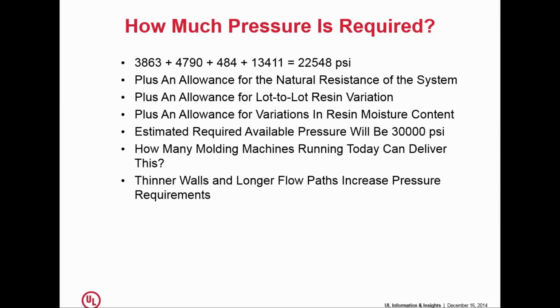And to move the screw, even if there's no plastic in the barrel, if you move a screw that's empty through an empty barrel, you will still get a pressure reading. And that pressure reading is just the natural resistance of the system, the natural inertia of the system. And for different machines, that number is going to be a bit different, but it can be anywhere from 2,000 to 3,000 psi, which must be added to this 22.5.